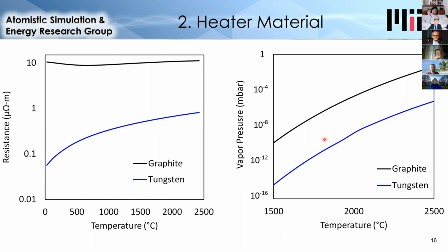The other property I'm showing here is vapor pressure, and this is an indication of the rate that the heater will evaporate when it's hot. And you can see that graphite across the temperature range, and especially at 2500 degrees Celsius, has a vapor pressure about 10,000 times higher than tungsten. Now, although it's much higher, graphite can still last several years. You lose about a millimeter of material per decade, but it shows you that tungsten is definitely preferable from an evaporation standpoint. And so in these experiments, we tried using both materials.